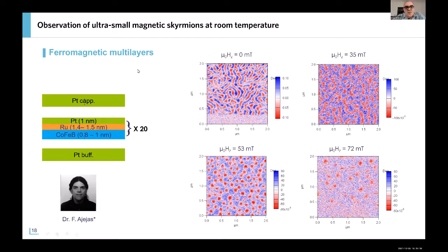We use ferromagnetic multilayers like this that we can prepare by sputtering deposition. So they are not epitaxial systems, but they are deposited by sputtering deposition. And you see, in this case, we use cobalt iron boron, ruthenium, platinum multilayers. So we have this break of symmetry in terms of the materials that are around the magnetic materials, and you have here typical thicknesses of 1 or 1.5 nanometers.